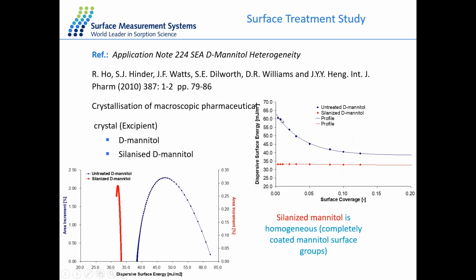So in this case, we have two different materials. We have unsilanized mannitol and silanized mannitol. This is looking at the dispersive surface energy, and the x-axis is looking at surface coverage. So this is the injections that we've introduced onto the surface of our sample. And the dispersive surface energy is as a result of your non-polar interactions. There's two things we can see here. The difference between our silanized and our untreated mannitol is that firstly, our silanized has a lower dispersive surface energy, and our untreated mannitol has a higher.